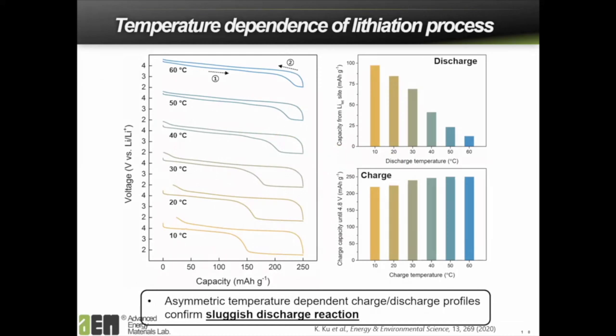Intrigued by this unexpected observation, we repeated the experiment at a series of other temperatures from 10 degrees C to about 60 degrees C, and it confirmed that it is reproducible. And more interestingly, it showed that the discharge reaction is much more temperature dependent than the charging reaction. If you look at the low voltage plateau here, it is the longest at 10 degrees C, but it almost disappears at 60 degrees C, where the normal discharge curve is recovered. And it strongly supports that the discharge reaction is asymmetrically more sluggish than the charging reaction.